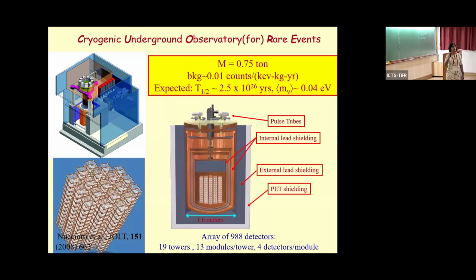CUORE. This is the tellurium, which I told you had a 30% enrichment. So in this case, one could think of using a detector without enrichment, and so they started with that. This was one of the largest bolometric detectors which they started with. Here there are multiple crystals arranged in an array, and you cool it down to 10 millikelvin, which is very similar to something, the Tintin idea is very similar to that. And here also the goal on the background was 0.01 counts per keV per kg year, and they expected to get a 40 millielectron volt sensitivity. But here they use a lead shielding, so there is a huge mass which is cooled to 10 millikelvin.